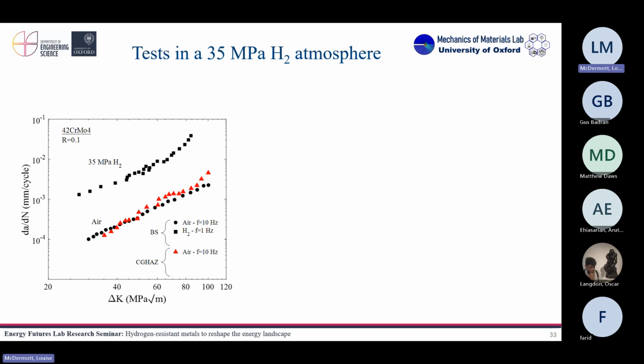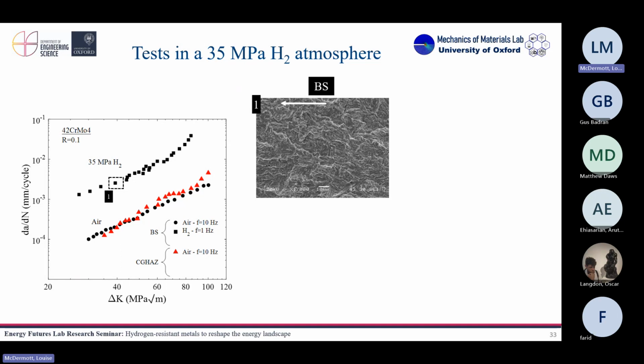So this is what happens in the material far from the welds at a high frequency. So that's interesting that I didn't have this kind of frequency effect here at 35 megapascals of hydrogen. So now we don't see that flat trend and that trend to overlap my, let's say, hydrogen-free behavior, but I see this parallel, let's say, crack growth to my master curves. And if I check here, I also don't see any striation mark. So remember, because that's done in hydrogen.